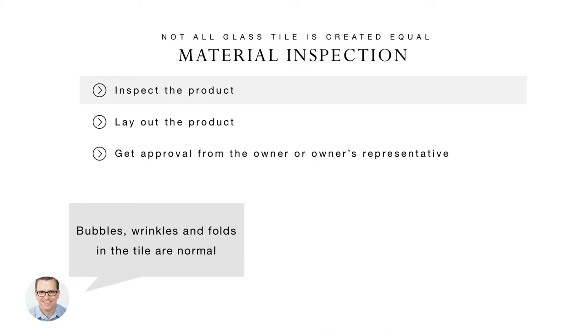look at the product. We do want to note that bubbles, wrinkles, and folds are normal in our cast glass tile. We do occasionally get the call from the concerned installer or homeowner who thinks they see cracks in their material. I can tell you almost 100% of the time those quote-unquote cracks are actually just the inherent wrinkles and folds in the material.